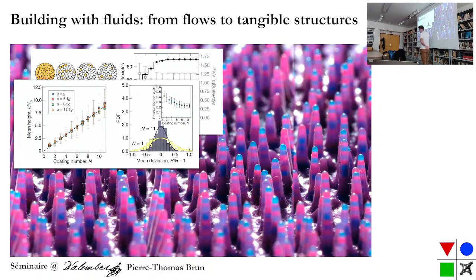If you look at the experiment, it feels like it's quite uniform. If you plot the data, you see that the size of the error bar is increasing, right? But actually, as a human, we're not sensitive to the absolute size of the error bars. You're sensitive to the size of the error bar with respect to the size of the object itself, right? And so if you divide the size of the error bar by the size of the object, actually what you see is that the relative spread is decreasing. So they're sort of almost converging, but not quite, right? There's always a difference between these hairs, but they're less and less different in some sense.